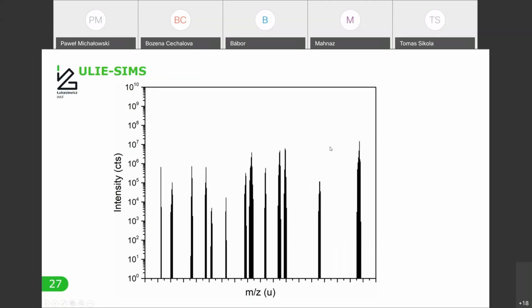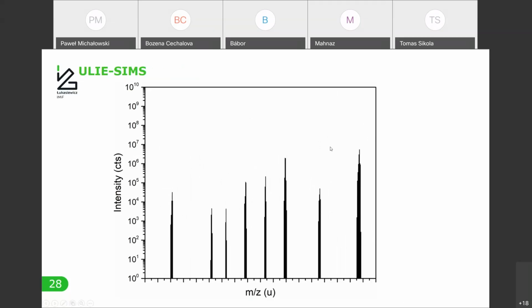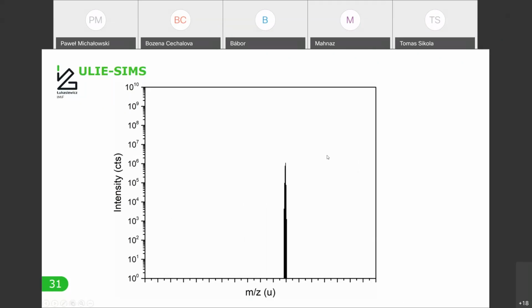And the important part here is that this particular result is 150 eV, but when we start to decrease the energy, some of these fragments start to disappear. So then in the end, we can only detect one peak, which means that with the decreasing of these energies, we can also probe how these fragments are formed. So which bonds within this organic molecule, how strong they are, in which order they will be destroyed.